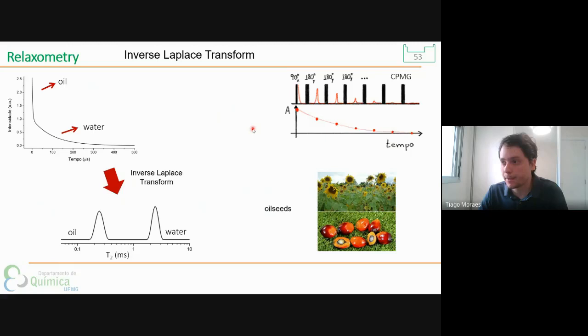To separate all these components, we use a mathematical procedure that we call the inverse Laplace transform. It's just like the Fourier transform, but it's a different mathematical approach. The idea is that we convert the decay. Here it is not the free induction decay; here it is the T2 decay from the CPMG. And we convert it into a spectrum, as you can see here, where the shorter relaxation time components, for example oil, will be transformed into this peak, and the longer relaxation times from water, for example, into this other peak. So here you can properly quantify how much water and how much oil we have.